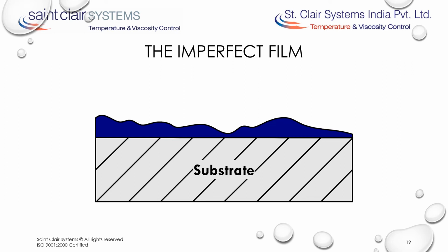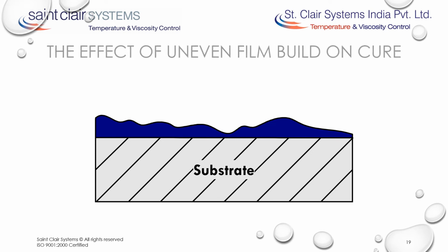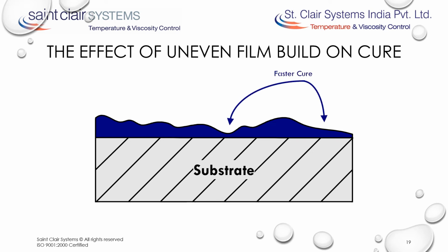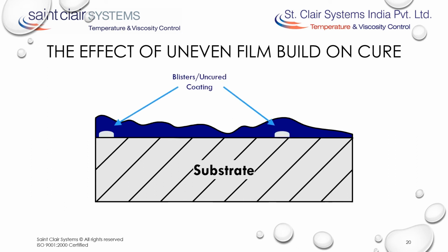But creating a perfect film requires perfect conditions. More often than not, however, conditions are not perfect. As we've already seen, if the fluid temperature is wrong, it will affect atomization, spray pattern, flow out, etc. The result is an uneven film across the surface of our part. This can have a significant impact on our film cure. Here we can see that thinner film areas will cure more rapidly than thicker film areas. This uneven surface will have a negative impact on bond performance. It's also possible to create blisters from solvent entrapment under the cured surface of the coating. Obviously, this will have a negative impact on bond performance. To make matters worse, if the thinner film areas are within spec, the thicker film areas represent excess coating being applied, which equals cost.